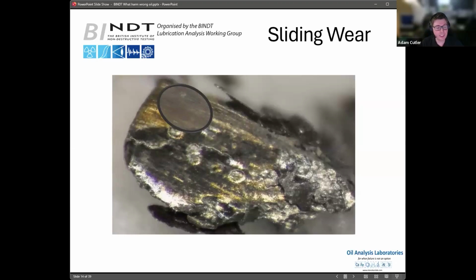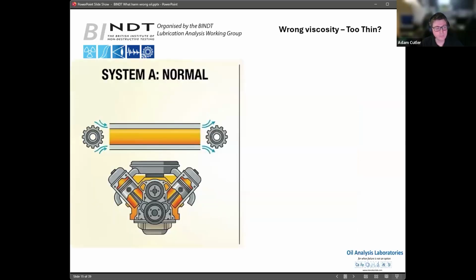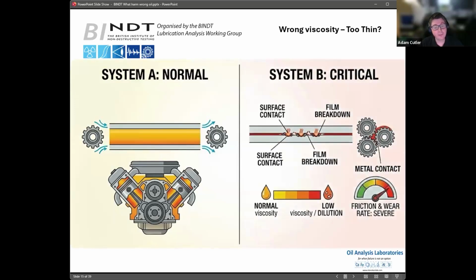And you can see on this particle here, we've got almost like a grain to the material. These are called striations, and these are significant in a sliding wear contact like I just showed. So if we have our normal system here with a full fluid thickness, and if we have one which has got too thin a film thickness, we can have boundary lubrication touching and then going beyond and actually breaking that and getting to metal contact. And this leads to increased wear in the system.